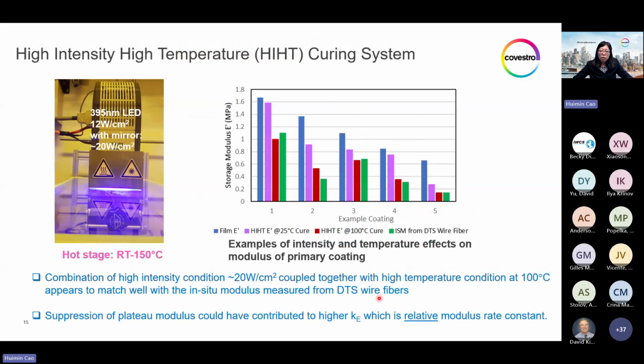And this is a very well-known fact in the industry. But to prove this in the lab, we custom-made this curing system having an LED lamp with a mirror design achieving very high intensity at 20 watts per square centimeter, much higher than a typical conveyor system, and a hot stage that can control temperature all the way to 150 degrees C.